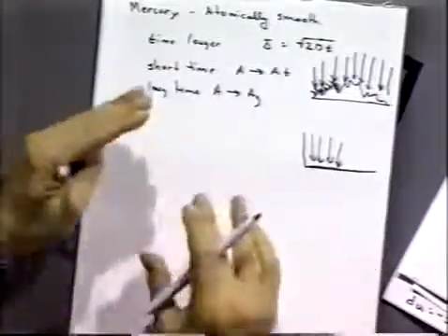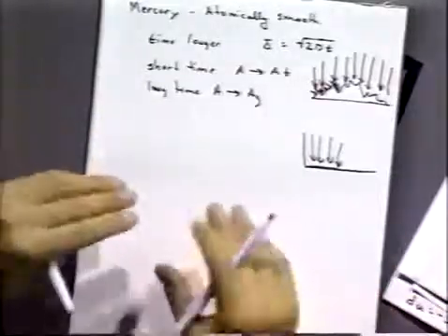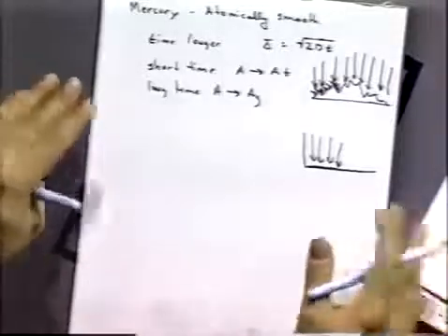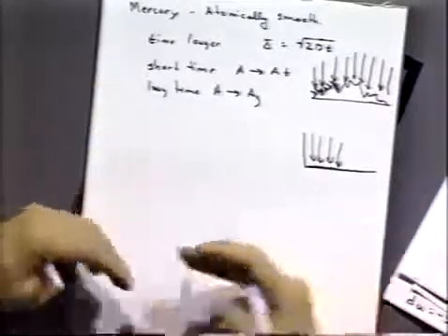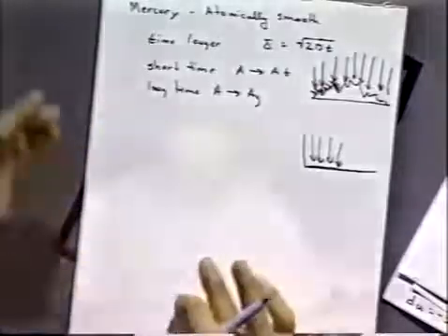We could step and look at the current at short times and at long times and compare the difference in the areas and see what the right area is, or whichever one you prefer to use. The problem is at short times we often have to worry about this charging current and the potentiostatic limitations, and at long times we have to worry about these other things. So you have to be very careful in these sorts of experiments to correctly account for the other problems that you're going to have. Actually, a better way to do that is to measure what they call an adsorption.